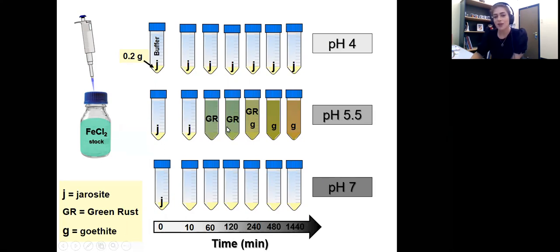And then this green rust gradually transformed to a goethite phase by the end of the experimental period, which was 24 hours, and it was a short-term experiment. So it was different from the acidic pH. And when I increased the pH by about 2 units, the rate and extent of this transformation was even faster.